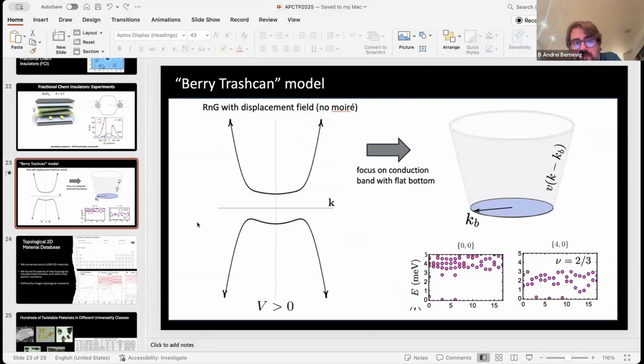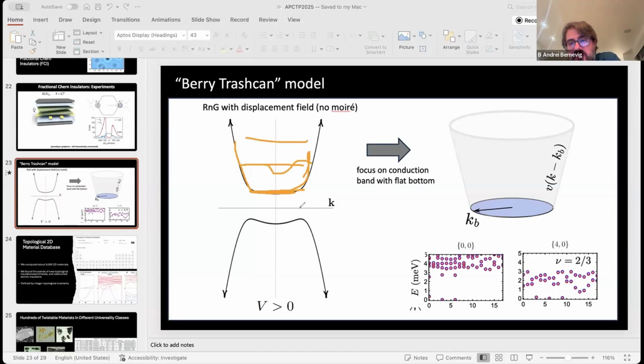Then for example, in rhombohedral graphene, this is a remarkable system because the flat portion of the band is not several flat bands, or even a flat band separated by a gap from another band. You have really a gapless dispersion. So how a gapped topological state can appear in a gapless dispersion is not understood. When you have Landau levels, there's a single-particle gap between them. But here you have a flat bottom and then highly dispersive walls, so the situation is very different from a Landau level. So why do we see fractional quantized conductance here?